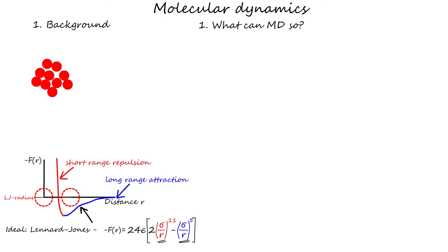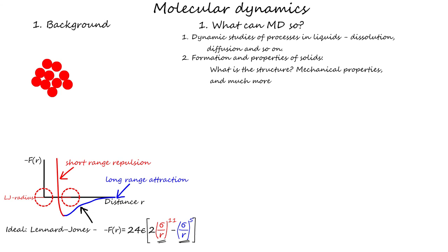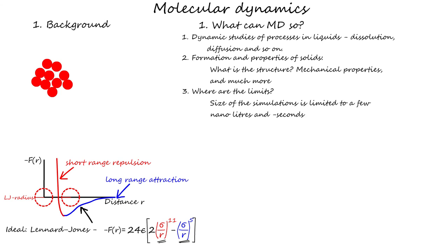So what can molecular dynamics do? MD can look at the dynamics of processes in liquids on atomic length scales, such as diffusion, dissolution, and so on. It can also look on the structures formed by the atoms in particular situations. Generally, MD is a powerful tool, but it is not the silver bullet it is sometimes advertised as. It requires good information about the potentials, which may not be easy to lay hand on. In cement, this is a problem. Also, it is computationally expensive, as our case study from a Transcend project illustrates.